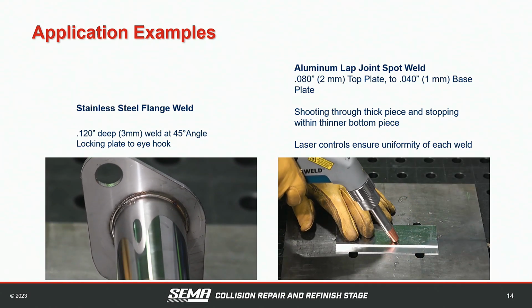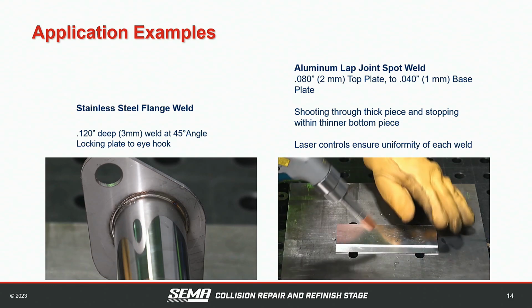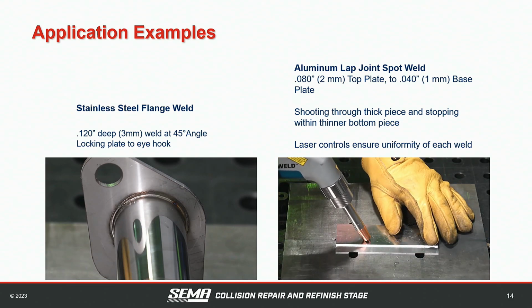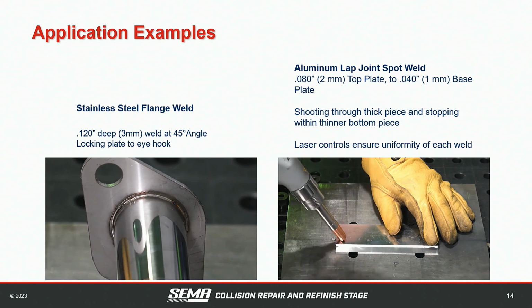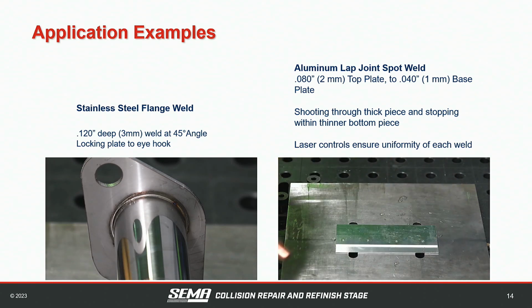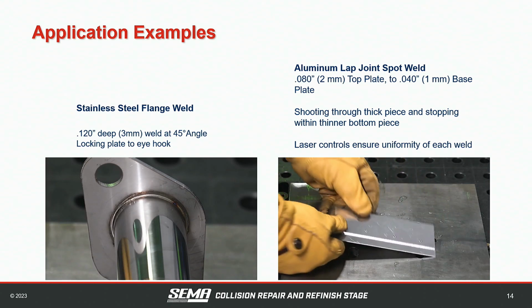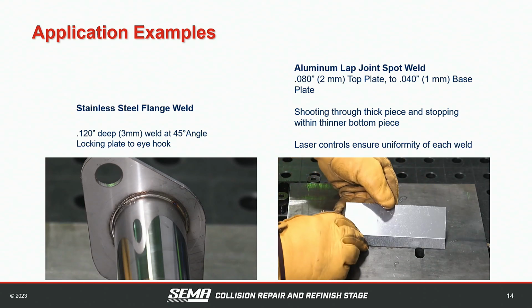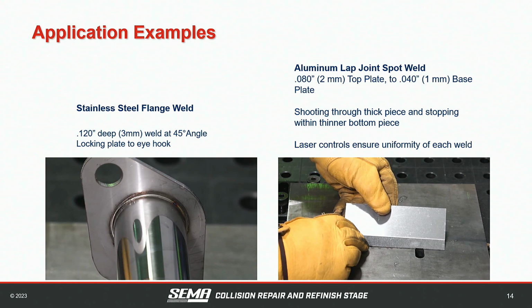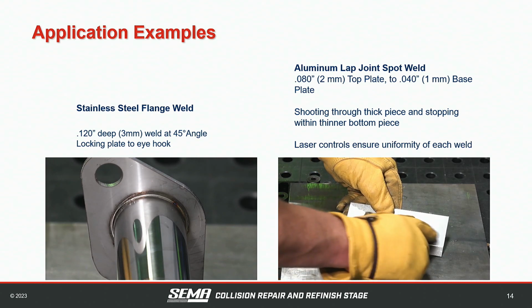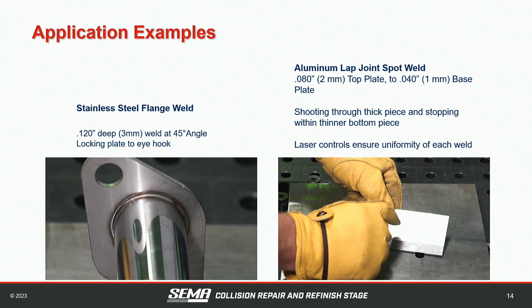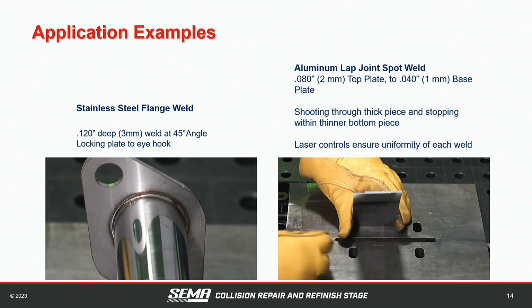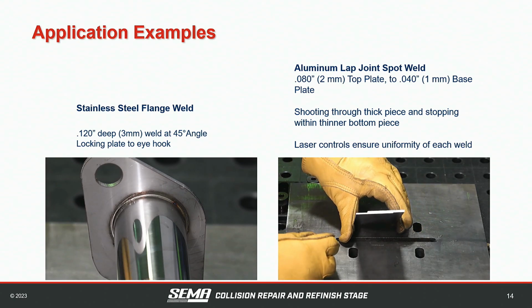It's showing the spot welding there, just going through two pieces of metal, so it's able to replicate a spot weld from only one side of the material, so long as they're making good contact. In this case, the lower piece of metal is half the thickness of the one on the top, and we were able to control the penetration through both materials very precisely. And for those of you that missed it, that's aluminum. They're doing spot welds on aluminum.